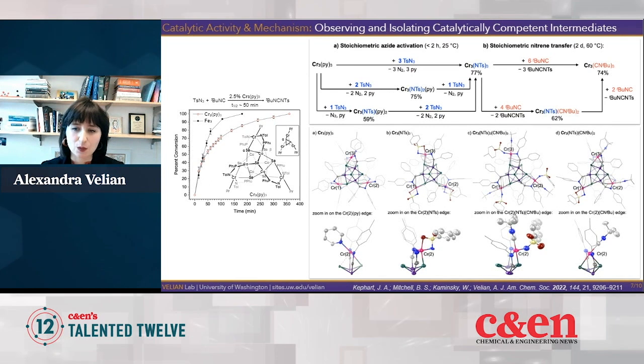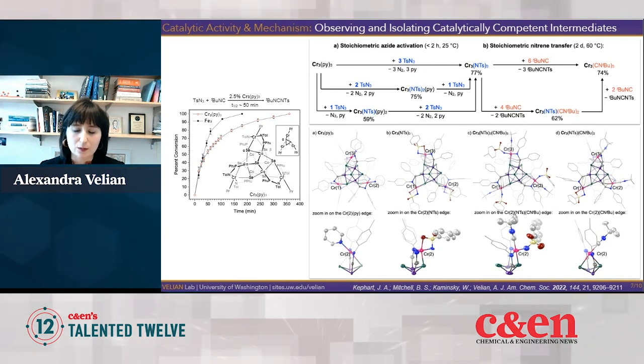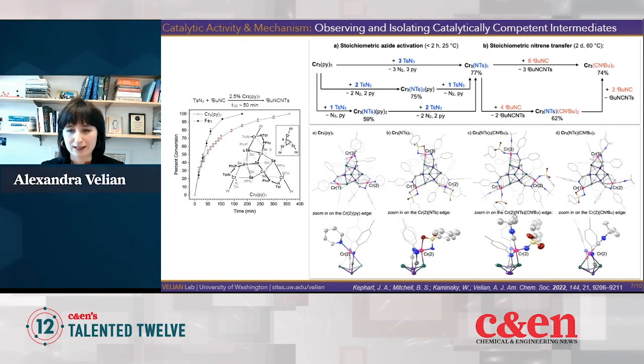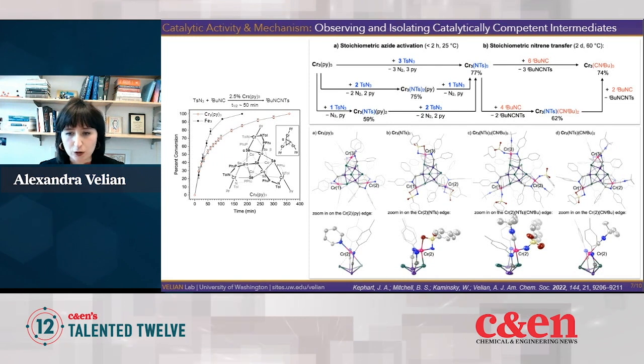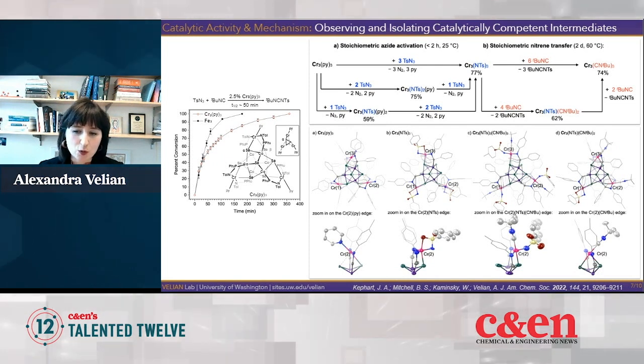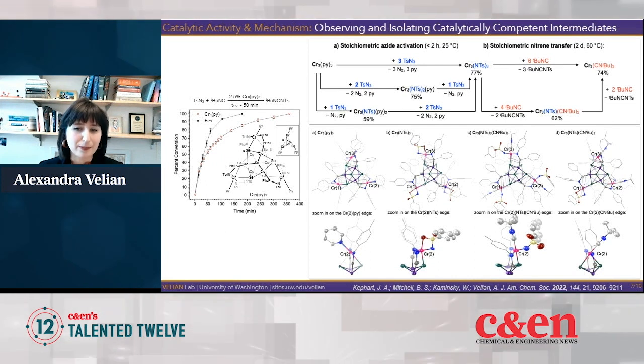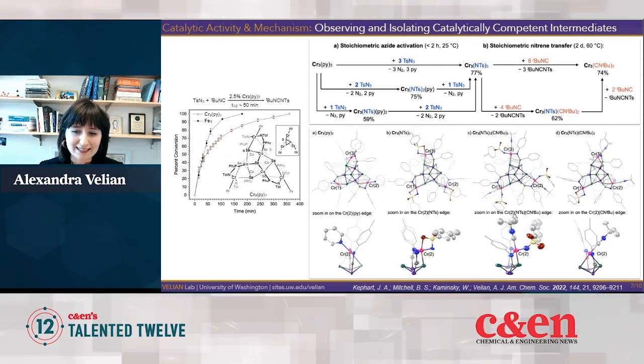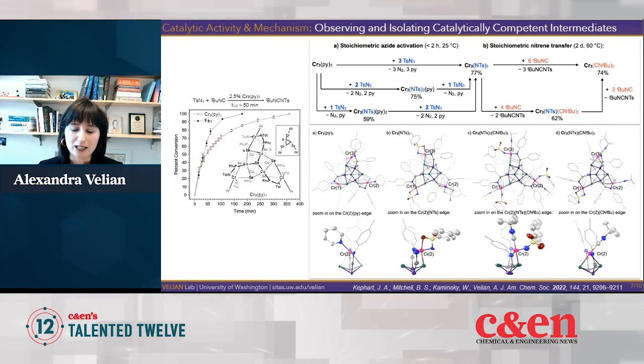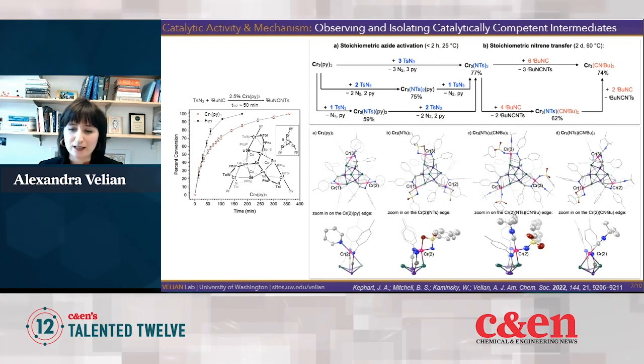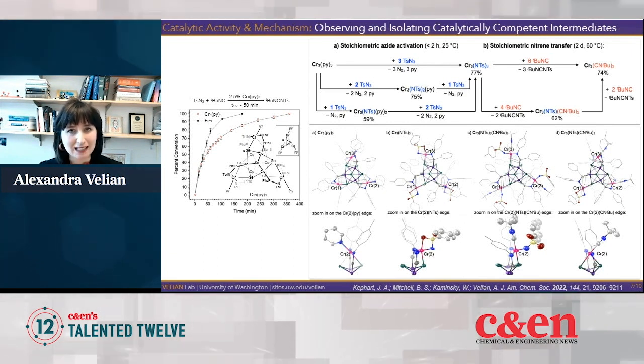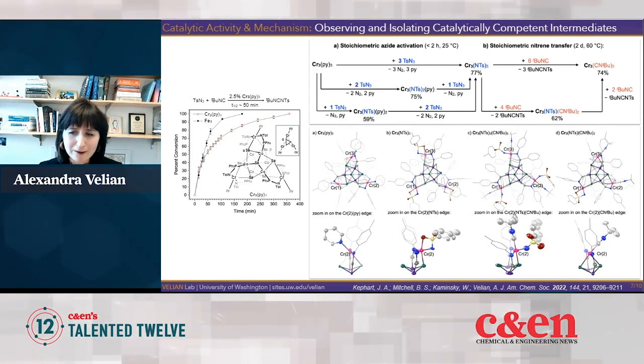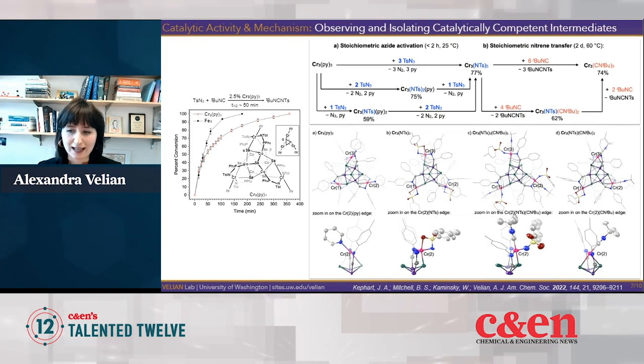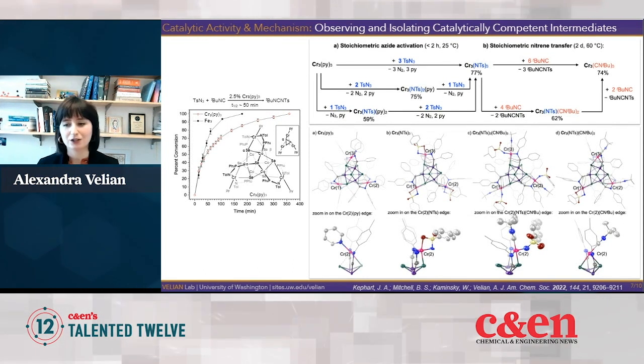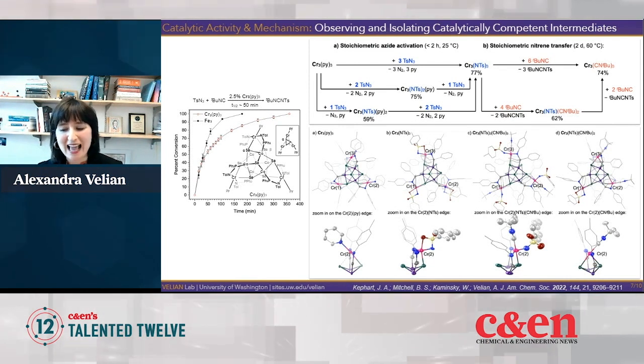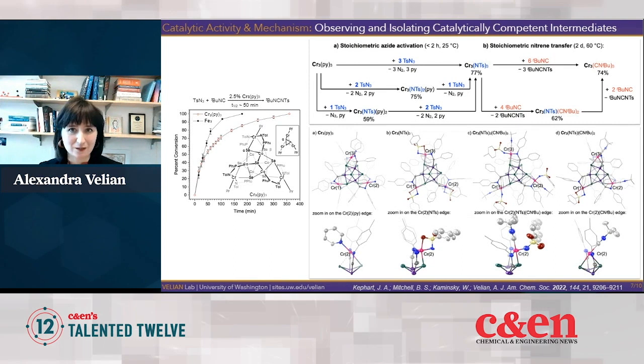Okay, so there's an inset at the bottom which highlights only a single edge site on these complex structures, and that's the one that I would like to draw your attention to. So if we start off with this chromium 2 edge site that binds a pyridine to it, upon azide activation, we can move to the next structure to the right. We can observe the chromium has changed its coordination quite drastically to accommodate chelation at this tosyl nitrene group. Finally, the isocyanide comes in and binds at this chromium edge site, releasing the oxygen that was previously chelating at the chromium. And this is actually a snapshot of the resting state of the catalyst also.